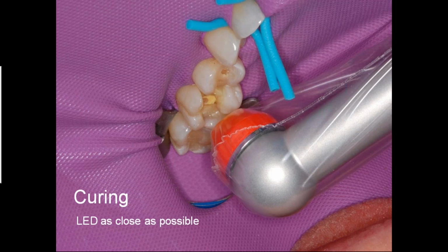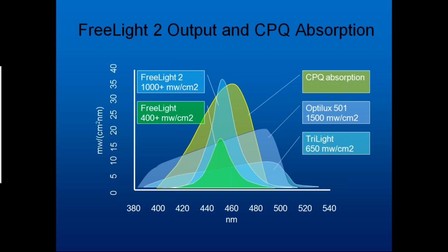So we're going to go ahead and cure this with our LED. A lot of these are like 1200 milliwatts. All you need is 10 seconds. Get as close as you can to the restoration. 6 millimeters away, you lose half of your energy. So these LEDs are certainly the way to go. That's why, because they're completely coordinated with the wavelength that activates the CPQ, about 460 nanometers. Much better than we can get with our halogens, so we're much more energy efficient, accounting for about 80% of absorption of that energy because of the CPQ being activated at that light wavelength.